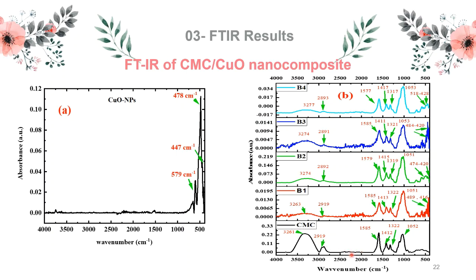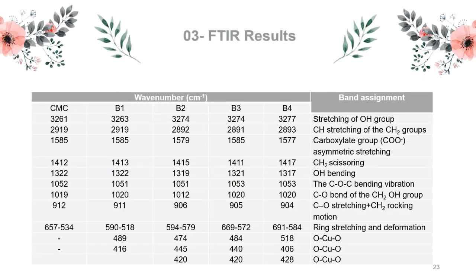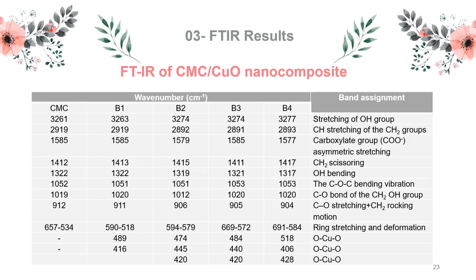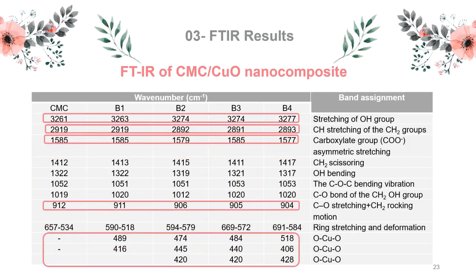Additionally, the figure shows that all samples possess high-intensity bands assigned to copper oxide nanoparticles, which may be due to the structural changes of CMC with copper oxide addition and to the increased concentration of copper oxide. All this evidence supports the formation of a hydrogen bond between CMC and copper oxide, as well as providing important structural modification information. This table presents the band assignment of the CMC and CMC copper oxide nanocomposite films. As we can see from the table, the characteristic bands of CMC have a strong shift as a result of the addition of copper oxide nanoparticles with different concentrations. The shift in the position of these bands confirms the good interaction between CMC and copper oxide throughout these absorption bands.